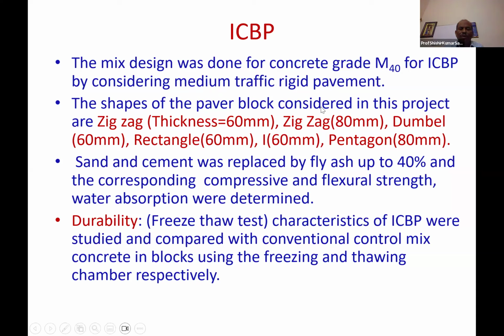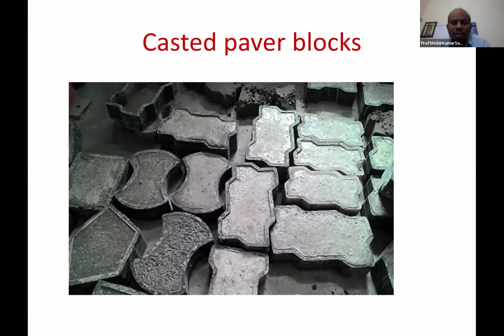The shapes of the paver block considered in this are zigzag 60 millimeter, zigzag 80 millimeter, rectangle, I-shape, pentagon, with sand and cement replacement by fly ash up to 40%. The corresponding flexural strength and water absorption were determined. For durability, the freeze thaw test characteristics of ICBP have been studied, compared with conventional control concrete blocks using freezing and thawing chambers respectively. These are the paver blocks.